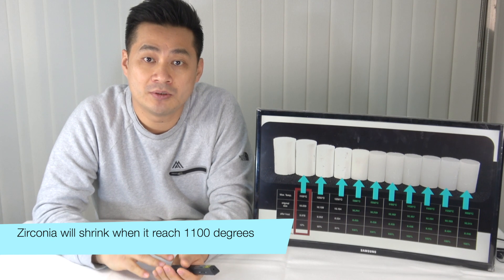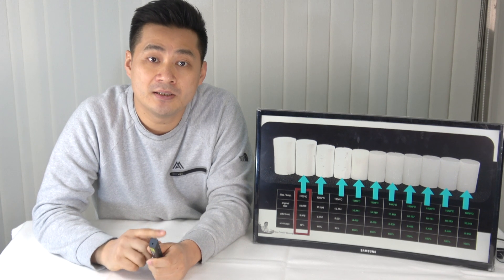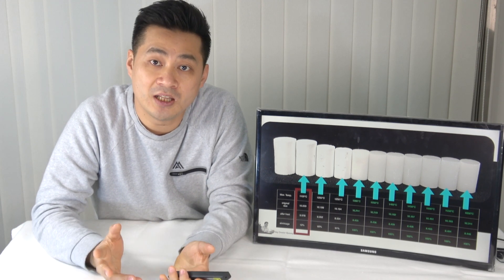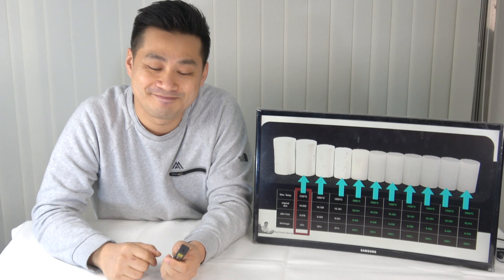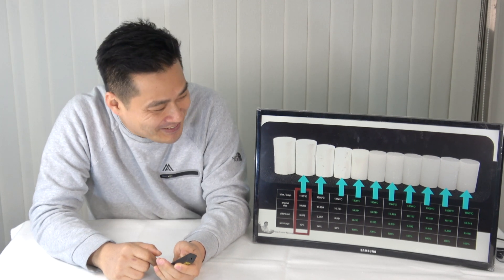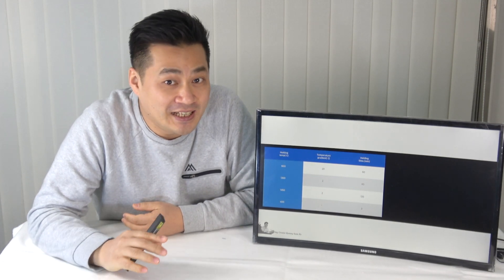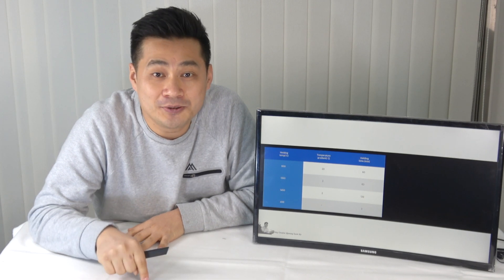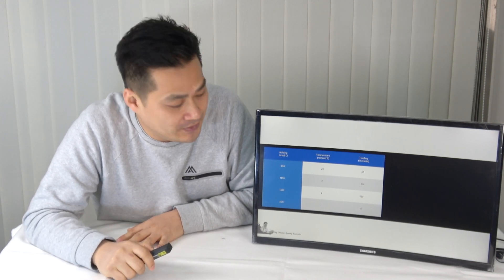This size change never goes back. So if you have a power failure at 1100 degrees, for example, you should remake the Zirconia crown — it can never come back, unfortunately. Now we know why a high ramp rate is used: nothing significant happens until it reaches 900 degrees, so we give a high rate to reduce time.